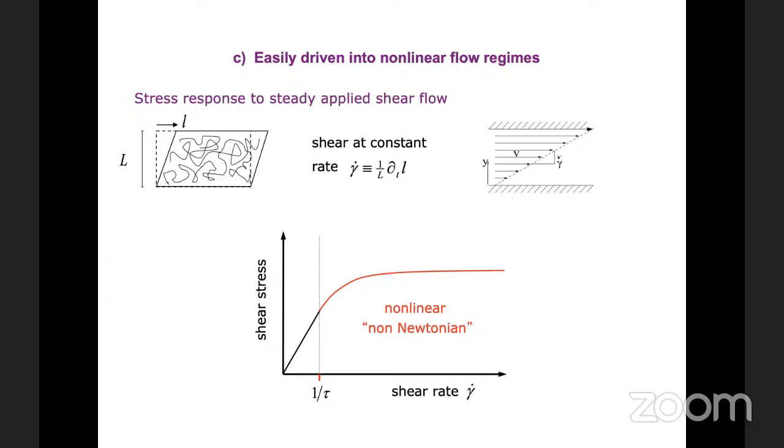So that might be a colloidal suspension, where you have glassy behavior above typically a packing fraction of 0.58, if more than 0.58 of the space is filled with colloidal particles rather than solvent. That's the so-called thermal glass transition, or you can think of jammed suspensions of soft particles where you have a jamming transition above 0.6. Oh, I've just forgotten the number off the top of my head, 0.64, I think it is. It depends a little bit anyway on the polydispersity. So things like foams and emulsions, for example, typically have a yield stress. And in fact, we're going to see an example of a yield stress a little bit later on.